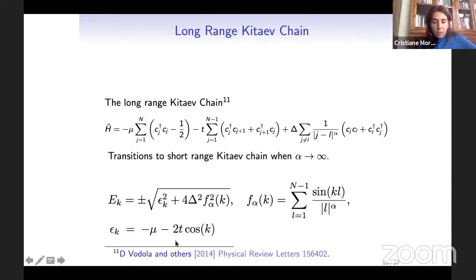So for k equals 0, if my mu is equal to plus 2t, my energy is still finite. It will be minus 2t cosine of 0 is 1, so it's minus 4t. So EK squared is some value that is regularizing this function. But for mu equal to minus 2t, this becomes positive, this is negative, this energy vanishes at k equals 0. So at k equals 0, this first term vanishes, and I just have this function f that is exhibiting discontinuity. This is the point where I expect to get some mess.